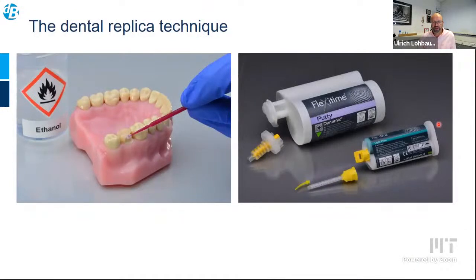And then there is another thing that is very unique in dentistry. This is the replica technique. Probably you already use it, but this is one thing that is not originally developed for dentistry but has been optimized for the use in dentistry. Those types of impression materials, so a stronger one that keeps an impression in place, and a lighter one, a more flowable, low viscous version, that is really copying the surface by making an impression. So we clean a fractured surface. At some point, we have a crown that cannot be removed from the mouth, or just a minor chipping that cannot be removed, and we want to inspect.